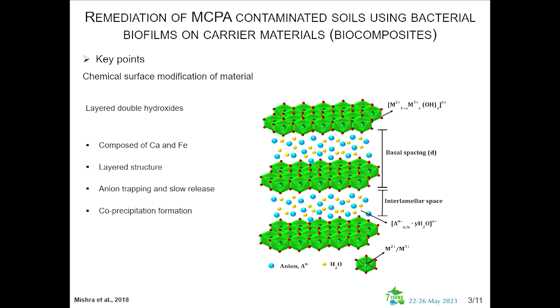Such materials can be obtained by co-precipitation, of two kinds mainly. The co-precipitations are obtained after mixing sodium hydroxide solutions and calcium and iron nitrate solutions in such a way that we have an increase of the pH during the reaction or a decrease of the pH. We will have some little differences in the characteristics of the layered double hydroxides, and we tested these two protocols during this research.